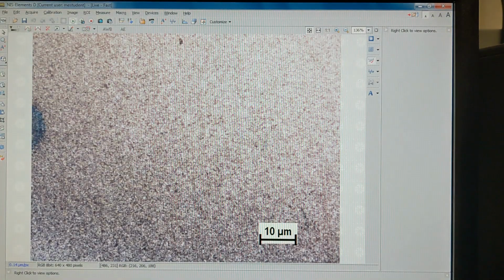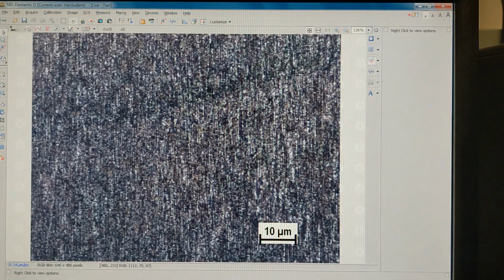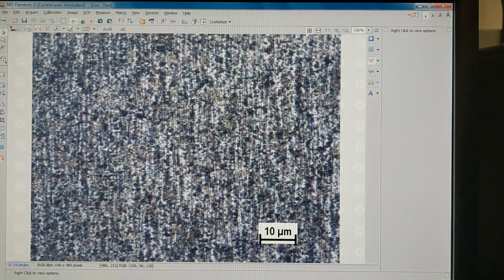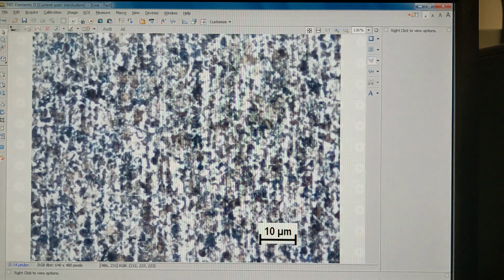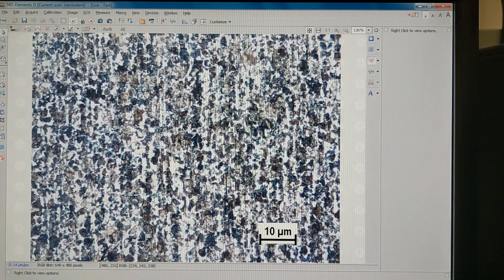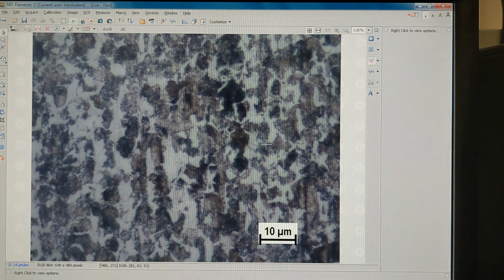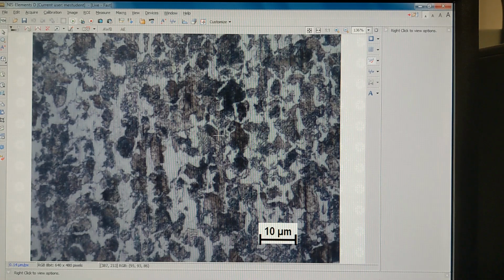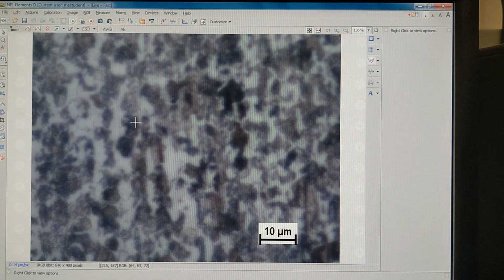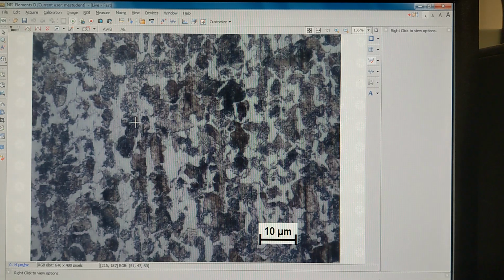And if we go back to our low mag, and then we go to our horizontal section parallel to the drawing direction, you can hopefully see, looking at this, I still believe we have some sort of linearity, but it is less prominent. This is 50 times. So here are our grains. We have nice pearlite here. No really big voids. This sample is maybe slightly over etched. When you get grains that look extremely dark like this, often that's a mark of over etching.